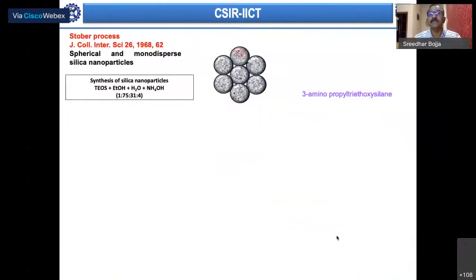Now how do we look at this? I'm talking about the functionalizing property here. If we don't functionalize, the core material and the shell material don't have a bond between them. I call it the friendly relationship between the core and the shell material. When this bonding is not there and you use such material for catalytic applications, there is every possibility that the catalyst around it can leach into the reaction, and by the end, all the shell material has leached into the reaction mixture.